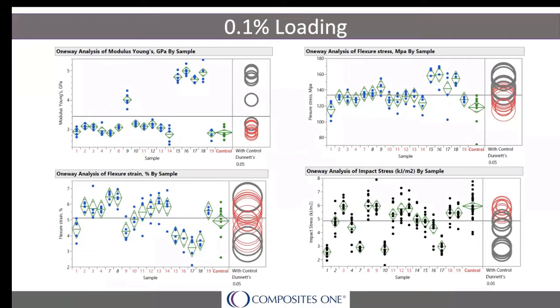So if we look at the flexural modulus results in the top left graph, you'll quickly notice the 5 samples I mentioned earlier have a significant improvement over the baseline. And their circles are in gray, reinforcing that they are statistically significant. And that's great news. Now let's take a look at the impact results in that bottom right corner for those same 5 samples and see if they affect the toughness of the resin.